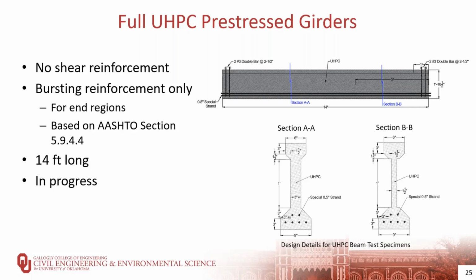The girder length was also changed from 18 feet to 14 feet to reduce the amount of material required, since it was anticipated that the UHPC would lead to shorter prestress transfer and development lengths. 2 UHPC girders have been constructed at this point, but there are still 2 full UHPC pre-stressed girders to be constructed at higher prestressing stress with different end region detailing.